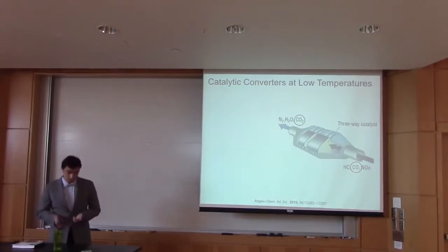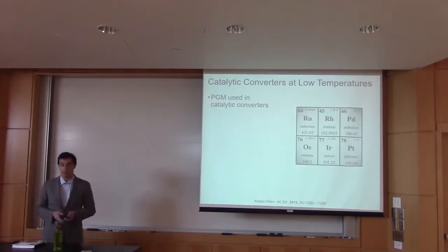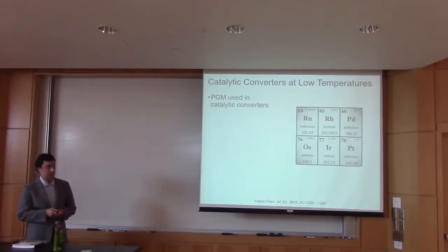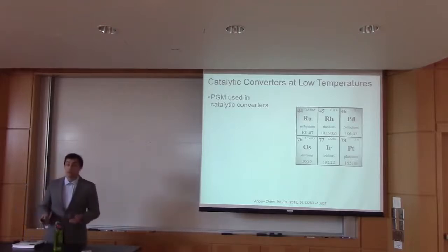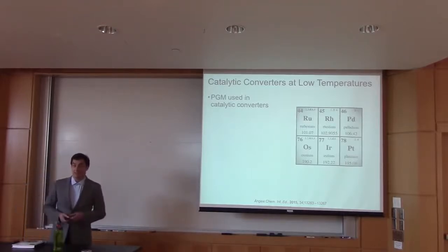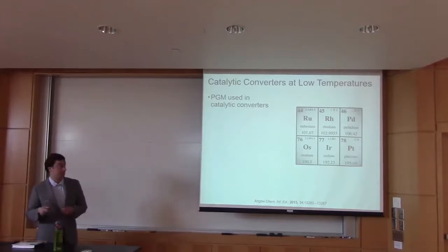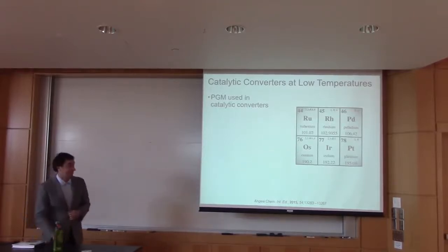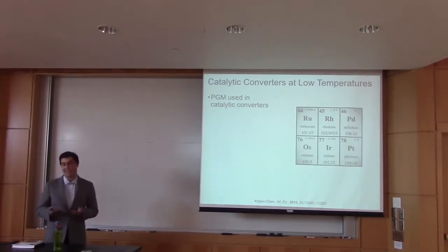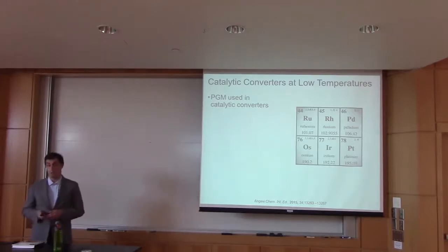focusing on. So in these catalysts, they use something called platinum group metals, which is this group here, seen on the periodic table right here. These are the traditionally very active catalytic metals, and tend to be the best performing, and they're usually the most expensive, but there's no point in trying to compete with them because they're the best. So in this project, we're not trying to outdo and fix these platinum group metals because we can't compete. Instead, we're going to take an area where they're weak, which is at lower temperatures, below 200 degrees Celsius, where they're not as good at converting this carbon monoxide to carbon dioxide.